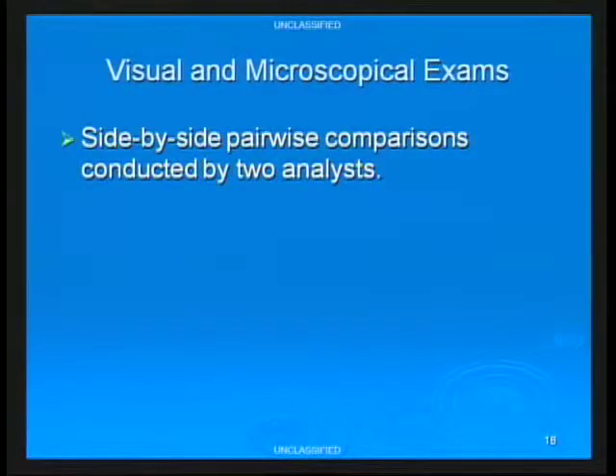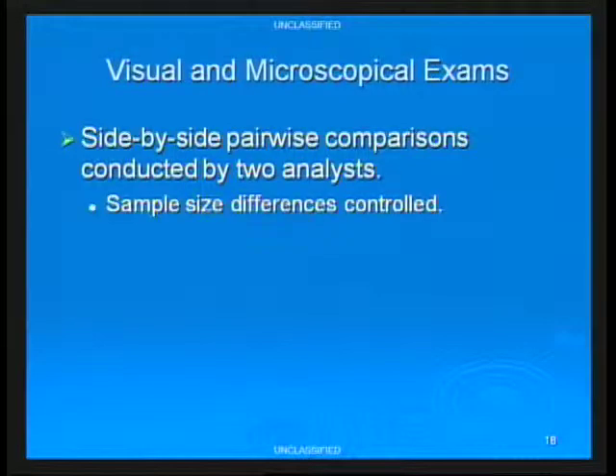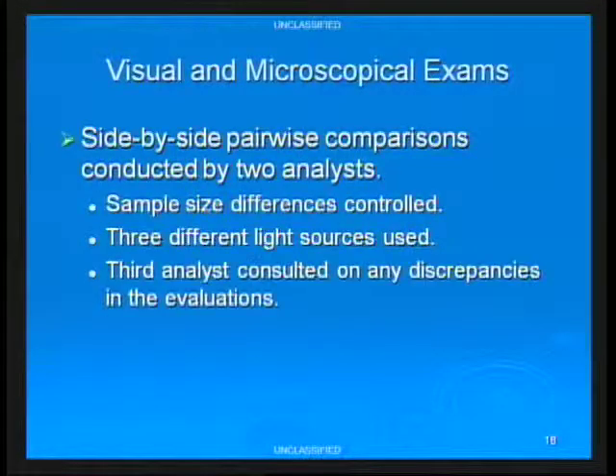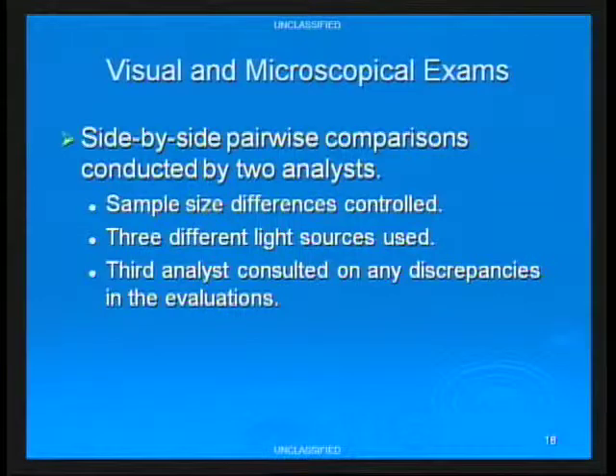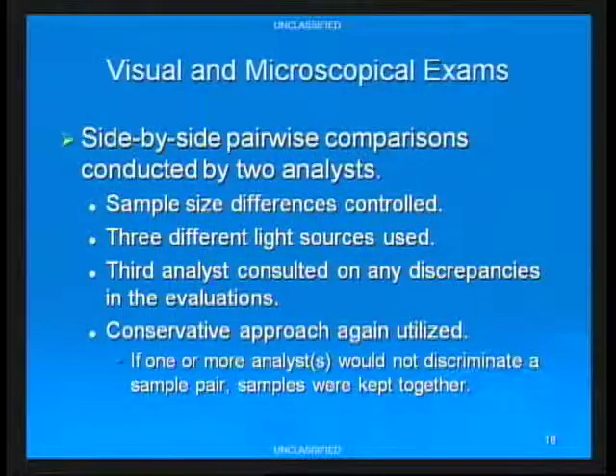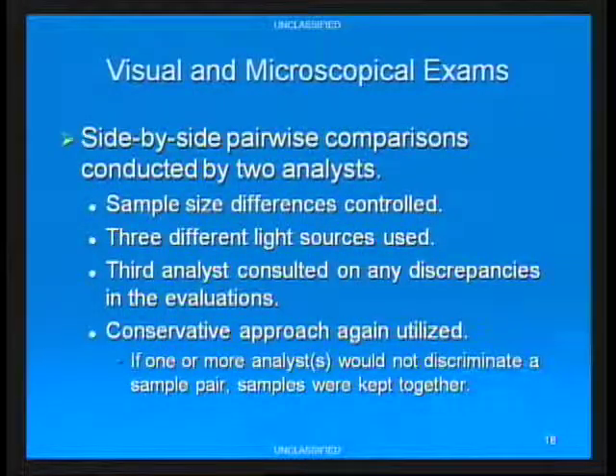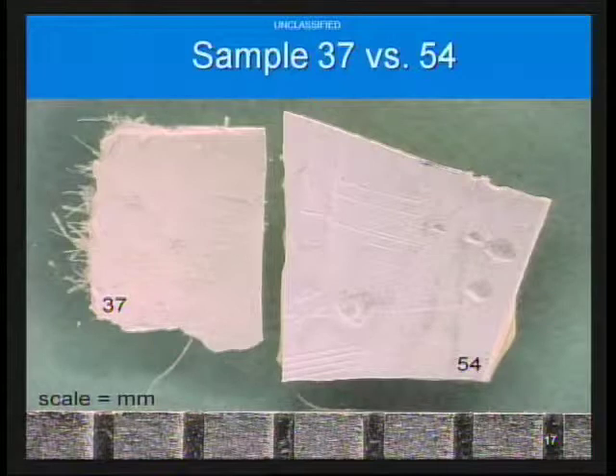Now back to visual and microscopic examination. With more manageable data sets, we did side-by-side comparisons. Two analysts worked independently, we had already controlled for sample size differences, and used three different light sources. A third analyst was consulted if there were any discrepancies between the two. Again, the conservative approach was that if one or more analysts said you couldn't discriminate, the samples were kept together.